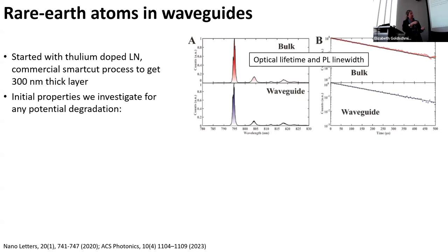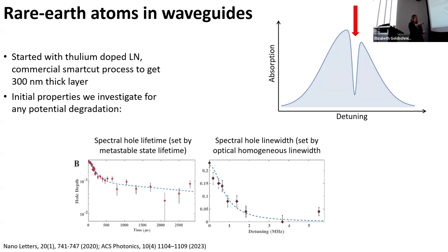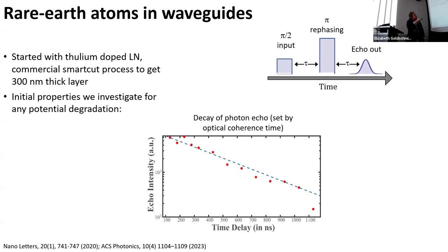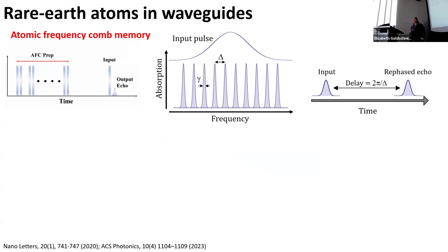We burned spectral holes, and we saw that both the lifetime of the spectral hole and the line width of the spectral hole were reasonable and were similar to what one would see in bulk thulium-doped lithium niobate. And we measured the optical coherence time, so we did a photon echo measurement and looked at the decay of that echo, and that also matched basically what you expect in bulk lithium niobate. Once we could do that, we did an atomic frequency comb memory, not for single photons, because our efficiency was very bad in our thulium-doped lithium niobate waveguide devices.